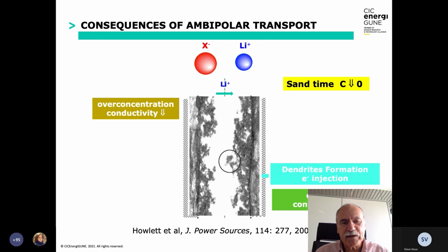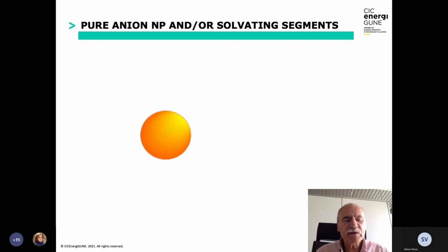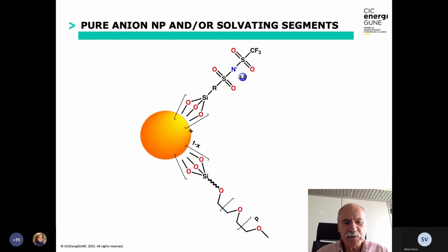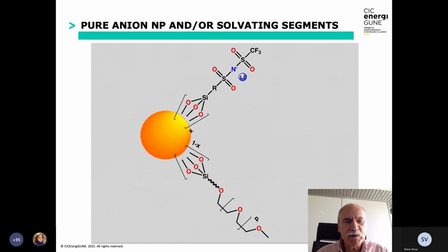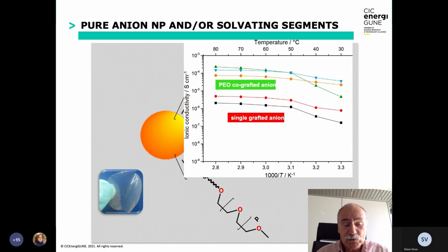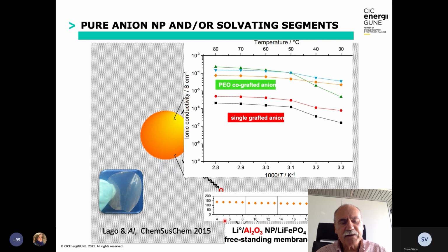This is obtained when the sand time, which is a parameter in electrodynamics, reaches 0. You start to grow dendrites. For solving this problem, we imagine to take a nanoparticle, graft the negative charge of the salt onto it, graft some PEO chain to make it more compatible, and immerse these nanoparticles into a PEO matrix. And then, as you can see, you obtain very nice mechanically sturdy membranes, which can conduct quite well lithium. In this case, the conductivity is due only to lithium, which can be the only mobile species. And as you can see, the LFP lithium battery cycles quite well with the nanoparticles with a membrane of 50 microns.